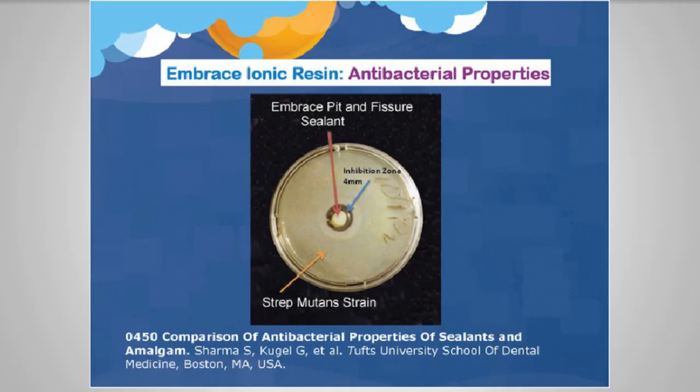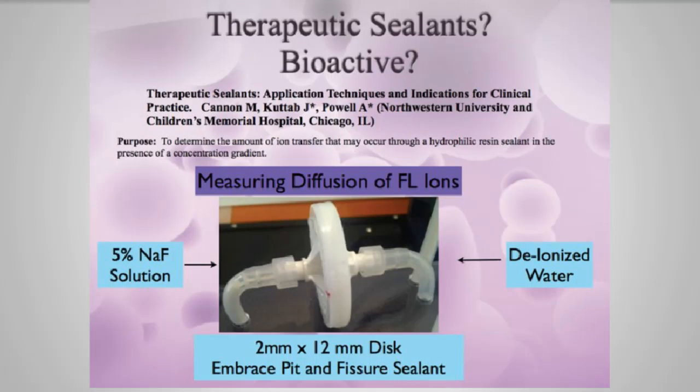It's also been shown to be antibacterial. In this test that we've done, it actually creates a 4 millimeter inhibition zone around it, just by having the Embrace material and the ion release that it has. This test was done by my pediatric dentistry professor, Mark Cannon, when I was at Northwestern.